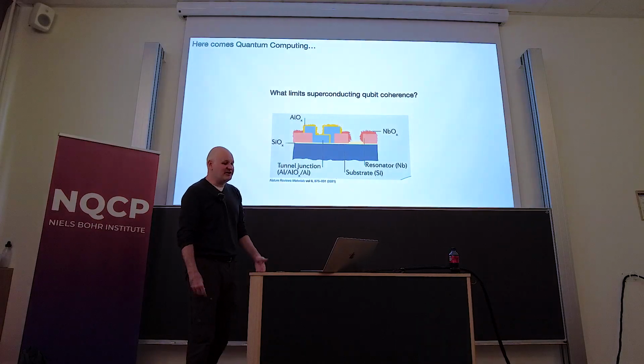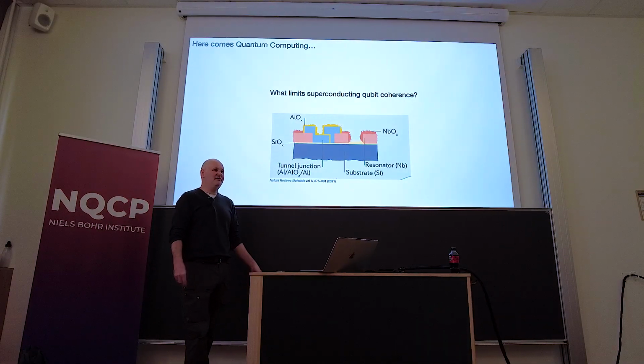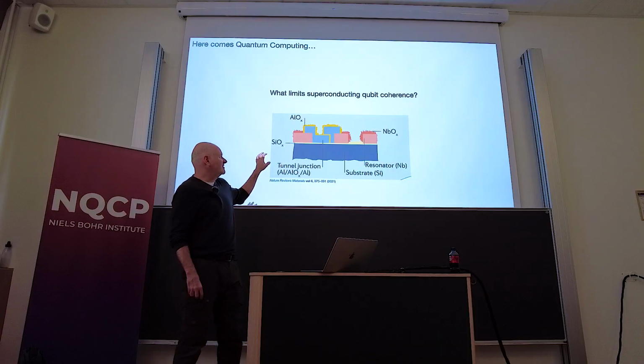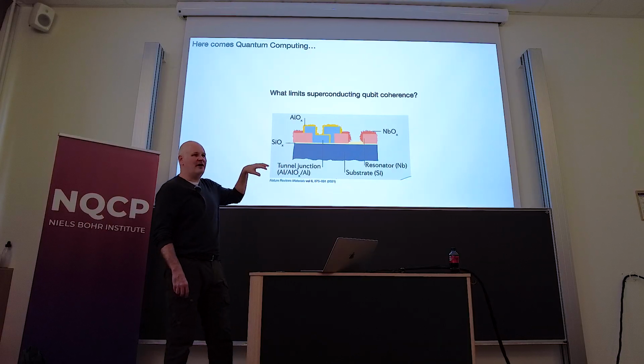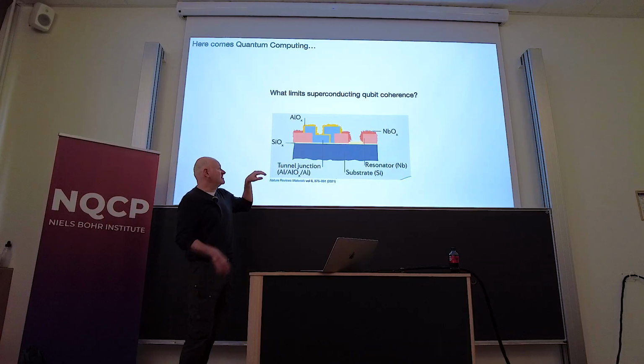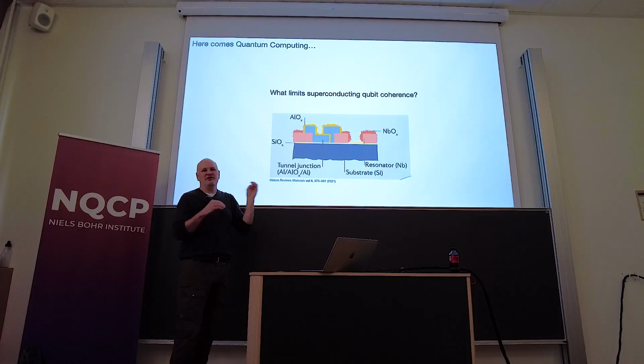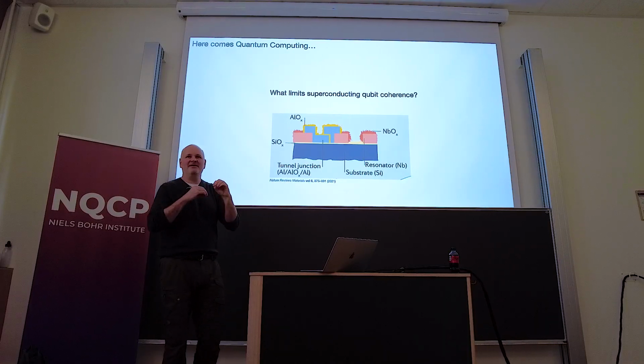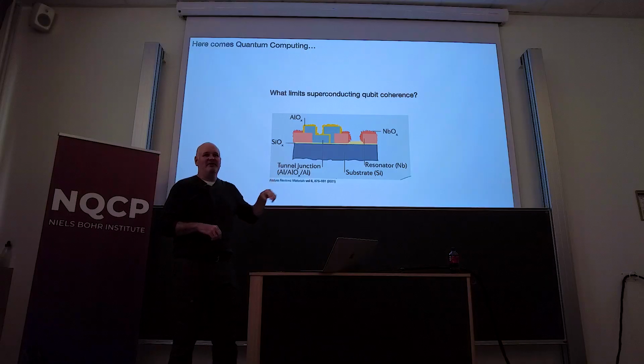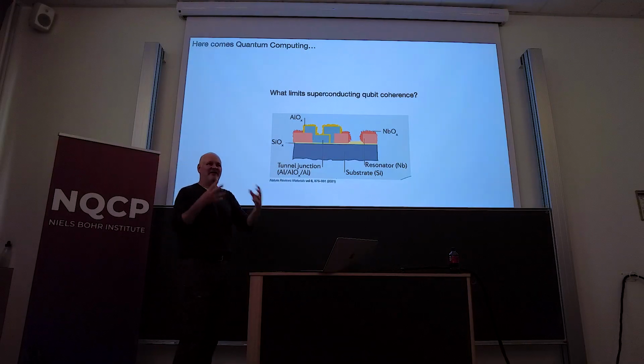His suggestion was that this might be due to stuff at interfaces. So all these little fuzzy things are different oxides that can grow on all the interfaces. And it's not just the surface interfaces, but also the interstitial interfaces between each layer that's deposited. It can be oxides, but it can also be organics. It's all the stuff that is basically a result of fabrication.